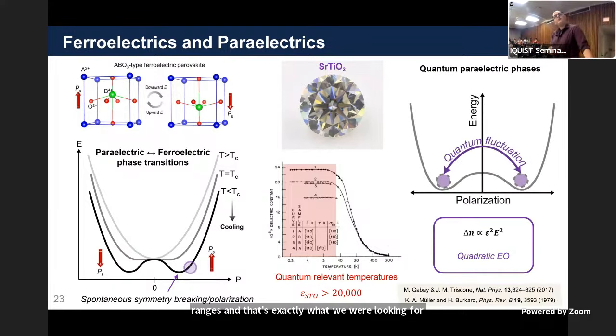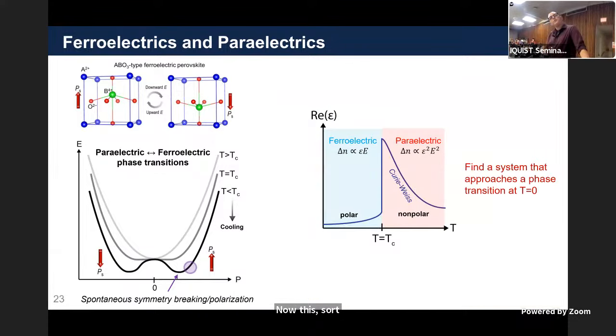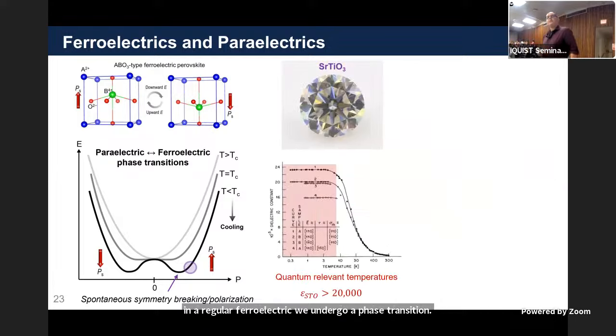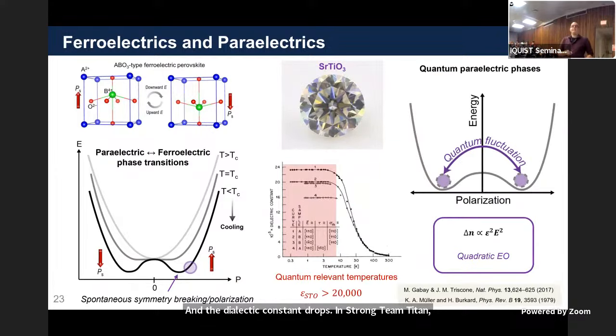Now, this fact that we'd actually never undergo a phase transition. So we go up and up and up, but then in a regular ferroelectric, we undergo a phase transition and the dielectric constant drops. In strontium titanate, we go up and up and up, and then we never drop. This is related to the so-called quantum paraelectric phase of this material.